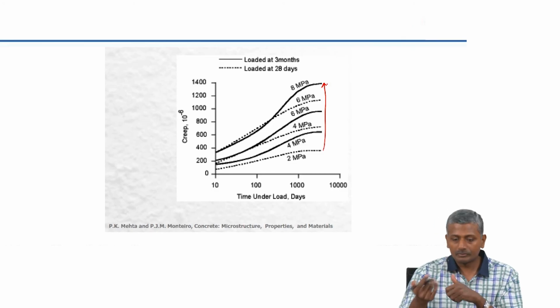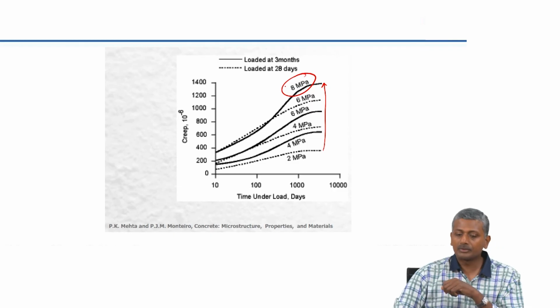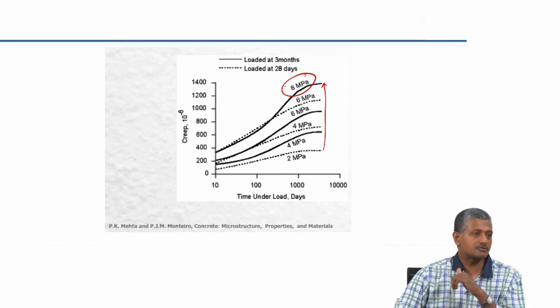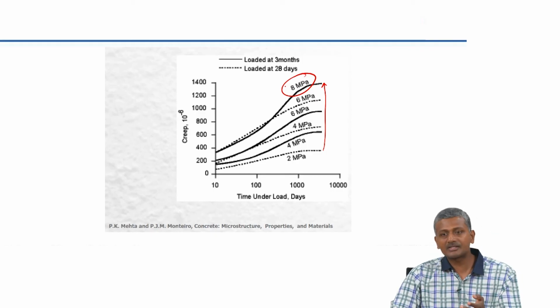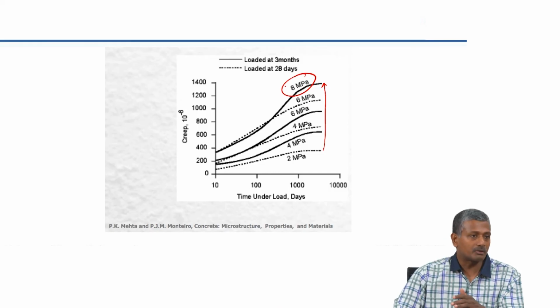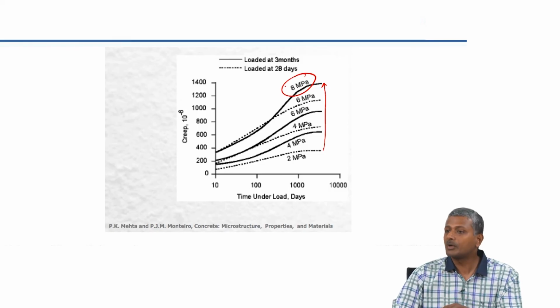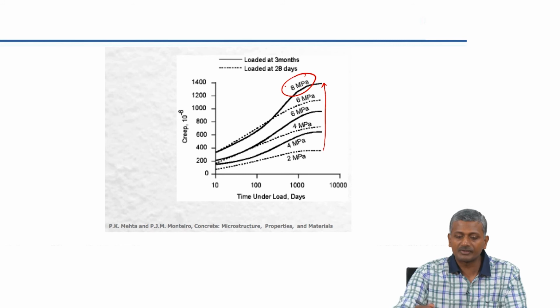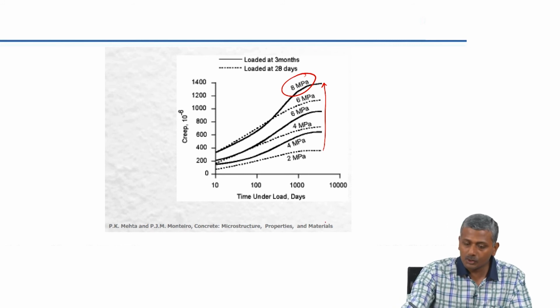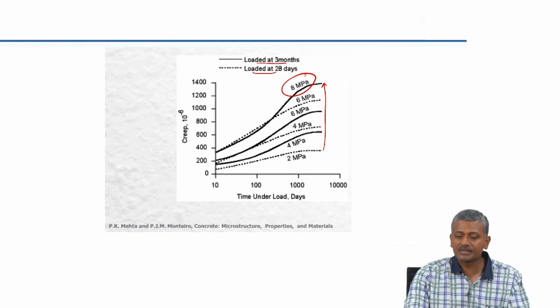Okay. So, for example, if 8 megapascals is the extent of stress that you expect will happen in your material, right. If you choose a material of M30 concrete as opposed to if you choose M40 or M50 concrete, the response to creep is going to be quite significantly different. Okay. So, all this is obviously for the same concrete. What is also shown here is the time at which loading is done, right.